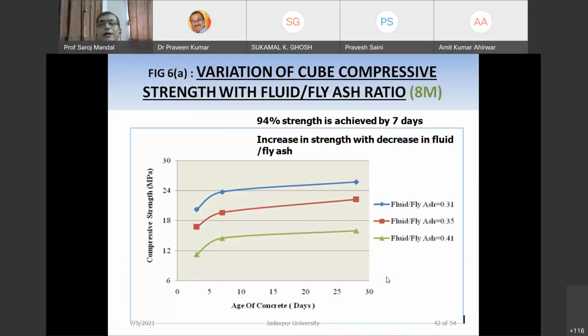Now, if we go to that 8 molar mix, that is the molarity of this NaOH is 8 molar, the age of concrete was measured at 3 days, 7 days, and also 28 days, right? Now, if we go to the fluid to fly ash ratio, fluid means all the water. It is ranging from 0.31, 0.35 to 0.41, right? So this is for 0.41, then this is for 0.35 and 0.31. It is quite natural. If we use less water, we get a higher strength. This is the compressive strength in all cases.